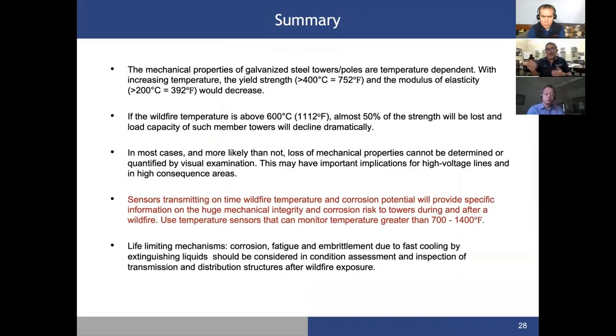To summarize, upon exposure to wildfires, materials change properties depending on the temperature of exposure. 400 and 600 degrees are temperatures that we should be concerned about. These are critical temperatures, especially 600 degrees, where you lose 50% of the strength.